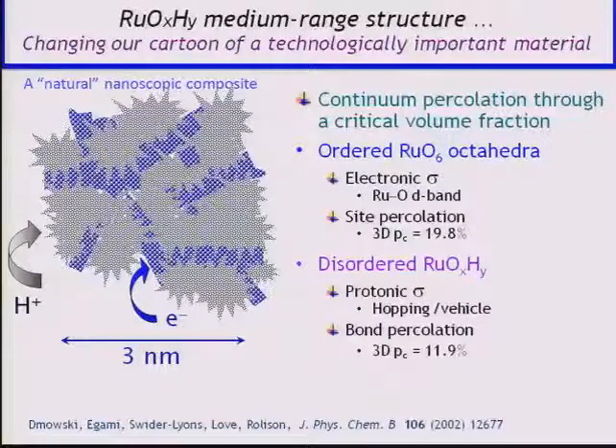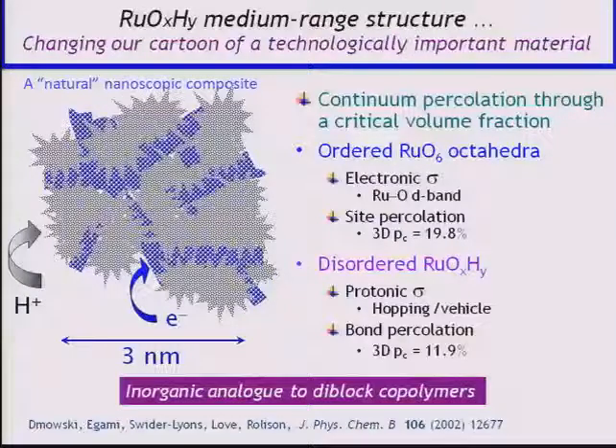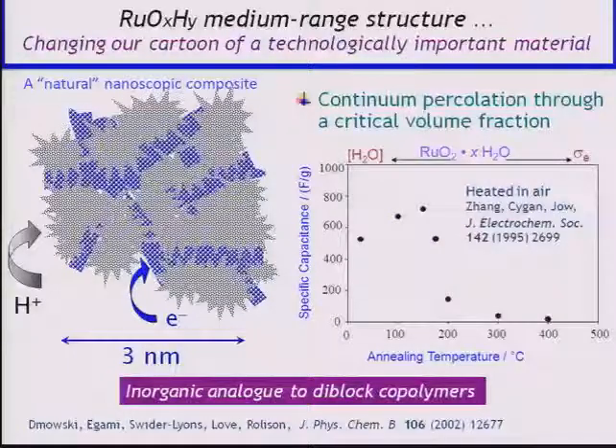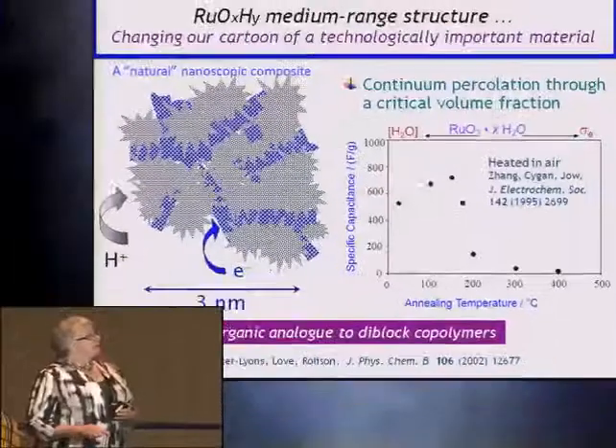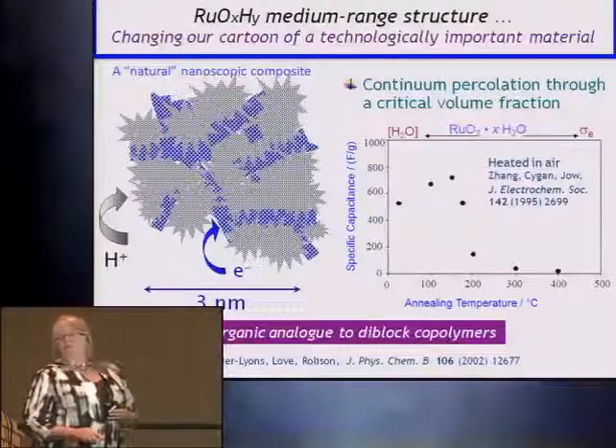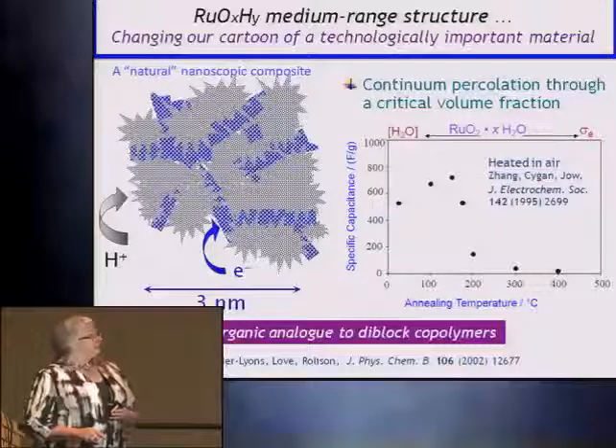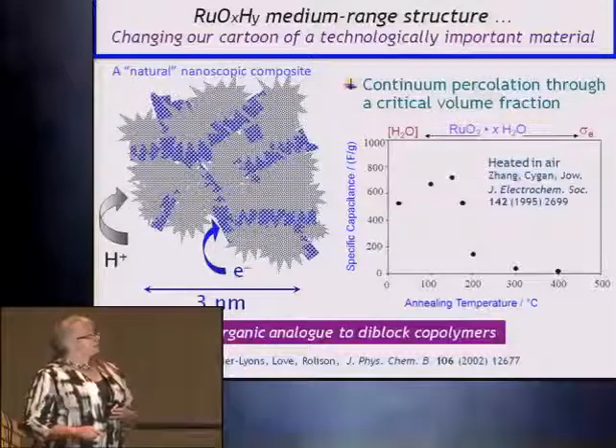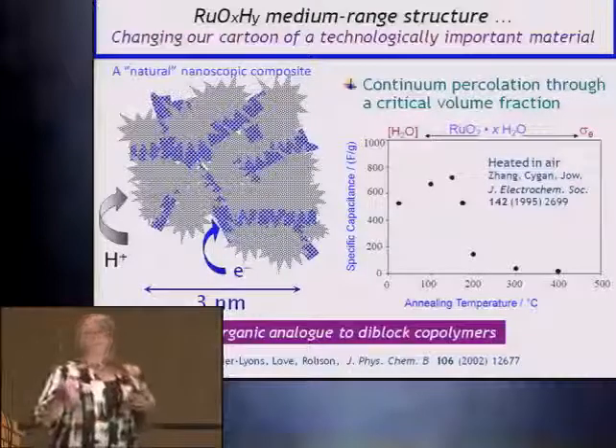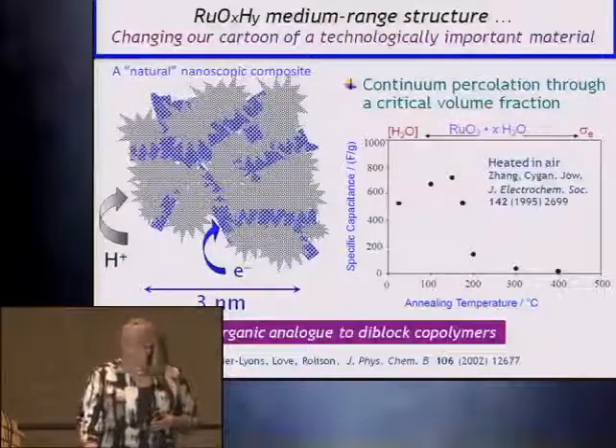And then as you put in, shall we say, more order, those regions get larger, and the proton conductive interfaces get smaller. I call this the inorganic analog to diblock copolymers, because you're putting the most important function, moving the protons and the electrons, at a very thin interface between the two. And that finally explained why, when you were working with hydrous ruthenium oxide, either very water-rich or very dehydrated, you had a volcano plot in terms of how much charge was stored. So here we've got a tie line. These two structures are storing the same amount of charge, but they have different fractions of the ruthenia versus the proton-conducting hydrous phase.